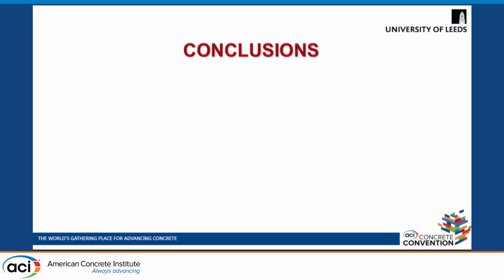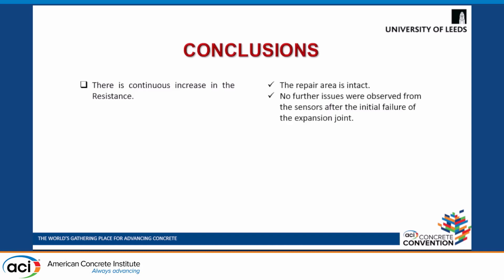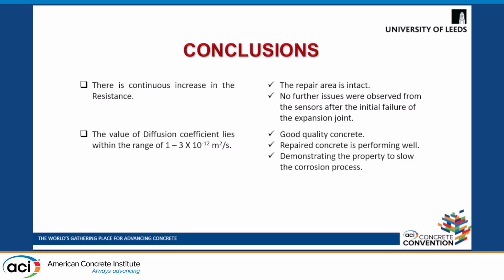So finally, we can conclude that there is a continuous increase in resistance, implying that the repair area is still intact. There are no further issues that were observed from the sensors after the initial failure of the expansion joint. The values of the diffusion coefficient lie in the range of 1 to 3 times 10 raised to the power minus 12. So the performance of the concrete lies within the range of good quality concrete, implying the repaired concrete is performing well and demonstrating the property to slow the corrosion process.